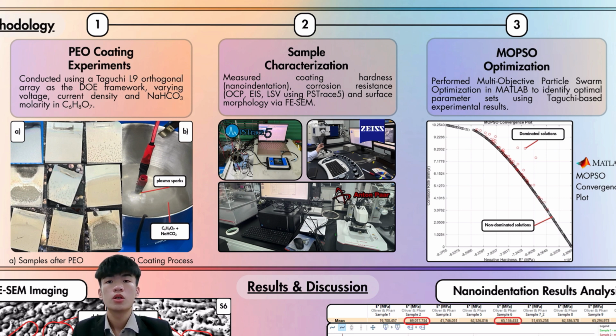Thirdly, the third surface characterization step was electrochemical corrosion tests, where again 3 different electrochemical tests were carried out on each of the 9 samples, namely open circuit potential, or OCP, electrochemical impedance spectroscopy, or EIS, and linear sweep voltammetry, LSV. These 3 tests were conducted in 3.5 weight % sodium chloride solution to mimic the real-world aerospace corrosive conditions. The tests were completed using a PalmSens4 device, and the data was analyzed via the PSTrace 5 software. Tafel plots were generated to derive I-corr and E-corr values, which can give us a picture of the corrosion resistance for the 9 different samples.